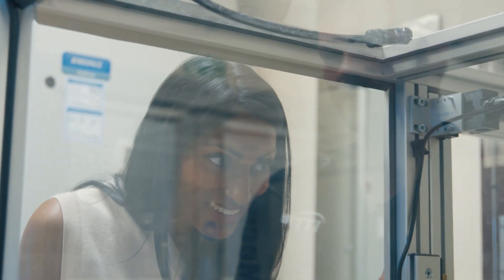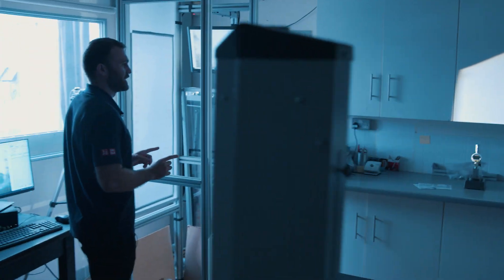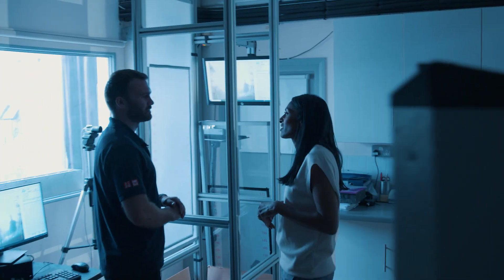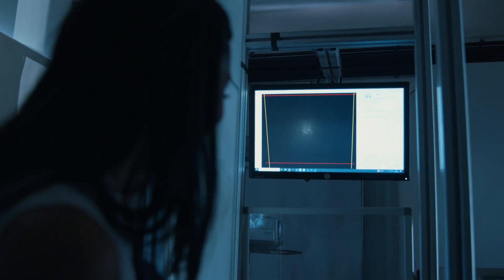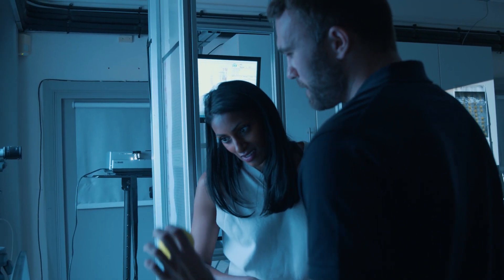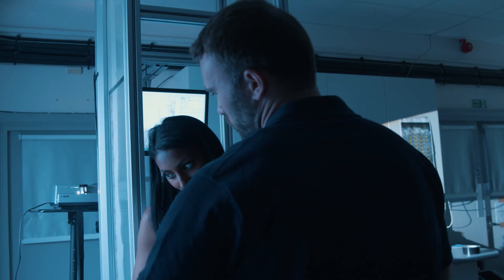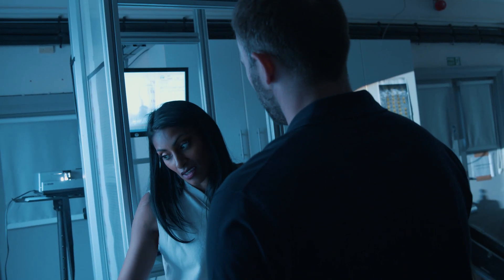Finally, from compression to the bounce test. We've got the light going, and we have a mirror there — shining against the mirror and coming back. The reason we're doing that is because we're not actually measuring the ball, we're going to be measuring its shadow. We have a calibrated screen and we know exactly how high the ball has gone based on its shadow, and that will record the height. We'll take four bounces for each ball, take the mean, look at the range as well, and make sure they're not too variable.